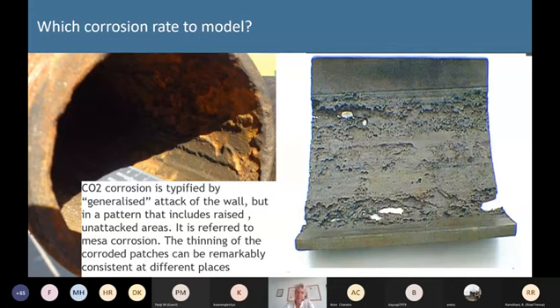There's a lot of discussion as to whether you're talking about localized or generalized. The reason I say it's generalized is that if I took an inspection of part of this piping, it doesn't really matter if I looked here or here or wherever, I'd probably get a similar impression of the corrosion. Whereas with localized attack, particularly microbial influenced corrosion or pitting type corrosion, it really is localized, and there may be no attack whatsoever elsewhere, and you've got to be very lucky to find pitting corrosion through general inspection. So what we're trying to model is the rate of attack at the bottom of these mesas. Really, how deep are we going through the steel in the areas that are not protected?